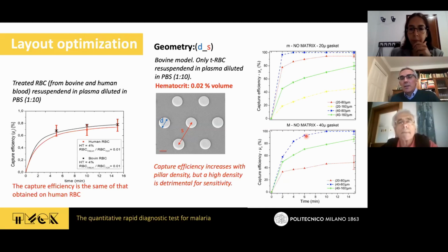What's the difficulty associated to this layout? The difficulty is due to the fact that the wiring for creating some electrodes on top of each of these nickel posts will become more difficult. It's really a problem of minimization of the number of electrodes that you put on top. Because don't forget that for the sensitivity in terms of detection, you want to have a large volumetric fraction, which means the volume of captured particle divided by the probing volume of the electrode must be high.